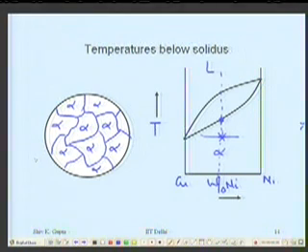Right? Yes, this has all become 100% solid. Now below this it shall all remain 100% solid, because that's the definition of solidus. But it is polycrystalline. It's not a single crystal. Usually the way we grow it, we solidify it, automatically it will form a polycrystalline one, because the nucleation at liquidus begins at more than one place. And then they each grow in size and some more nucleate as we cool. And that's how the amount of solid keeps on increasing.